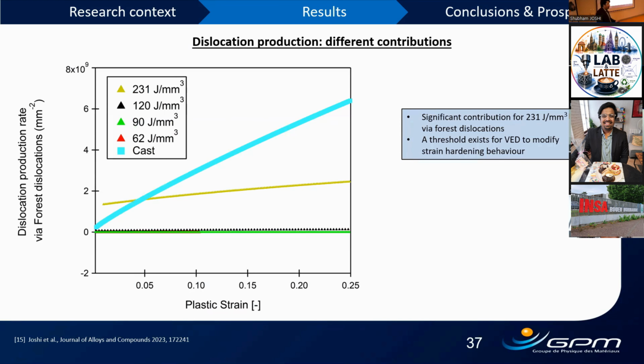But finally, the third microstructural feature which still needs to be understood is forest dislocation. If we compare the dislocation production rates by forest dislocation versus plastic strain, what we see here is that from 62 joules per millimeter cube to 120, this contribution is 0. And the cast one here is the maximum. And somehow the LPBF sample fabricated with 231 joules per millimeter cube is behaving somewhere in the middle. So what this analysis tells us is that with process parameters and this modeling, it is possible to tailor the strain hardening behavior according to the desired mechanical properties. And also, if we look at these LPBF samples, we can clearly conclude that dendrites are the most influential, not just for yield stress, but also for strain hardening, as given here.